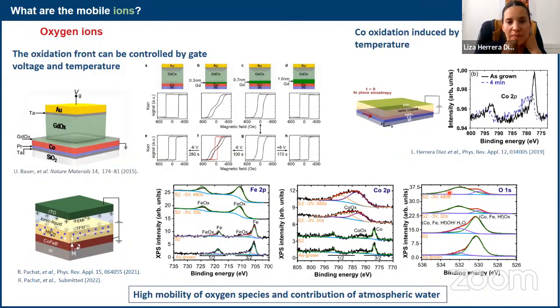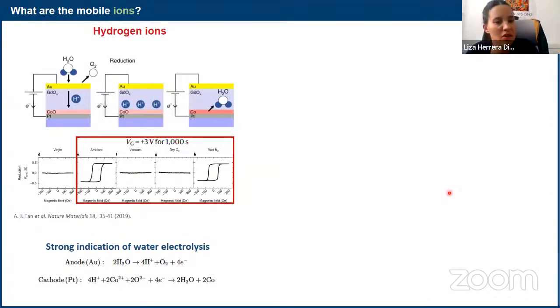But there's not just oxygen. The MIT group has shown as well devices in which there is a hydrogen based process. So they started off with cobalt oxide, and then they proposed that the water from the atmosphere could dissociate, and that there could be a proton diffusion into the layer. And then there is the hydrogen that's actually coming to reduce the cobalt oxide into cobalt, and that's how they go from oxidized to reduced through proton diffusion.